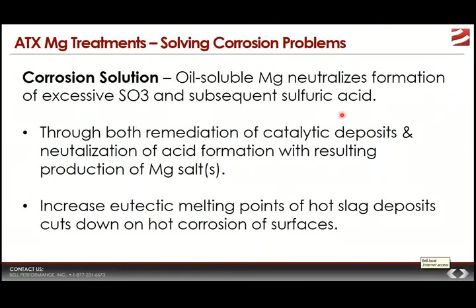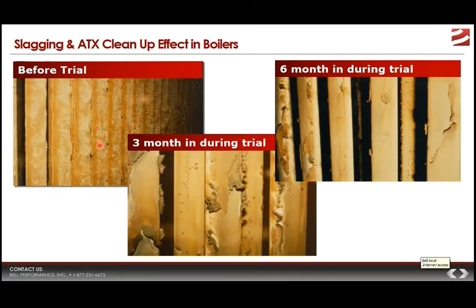But deposit control is something that oil-soluble magnesium is very effective at, but it's not the only thing that it does. It also helps solve corrosion problems, neutralizes excessive sulfur trioxide, and cuts down on the subsequent sulfuric acid formation. How does it do it? Well, a couple of different pathways. First thing that it does is it helps remediate or fix those catalytic deposits. So if those catalytic deposits, those vanadate deposits from the previous slide, aren't hanging around anymore, then they're not going to be in proximity when that SO3 gas comes and passes by them.